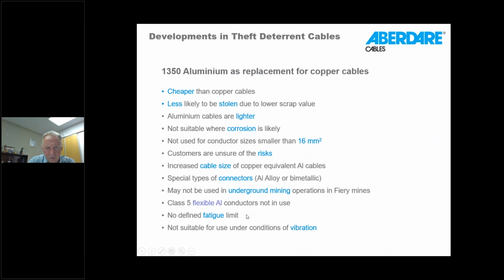There's no defined fatigue limit for aluminium in general, so the fatigue performance is quite good generally, particularly if you're using annealed aluminium. If you're using hard-drawn aluminium, it is definitely a problem, because any little nick or stress raiser on the surface of the wire will cause early breakage. So hard-drawn aluminium, we all know from aluminium wire armouring, can break very easily. But when you have annealed aluminium, and particularly the alloys of the 8000 series, that is not the case. So 1350 is not suitable for use under conditions of vibration due to this fact.